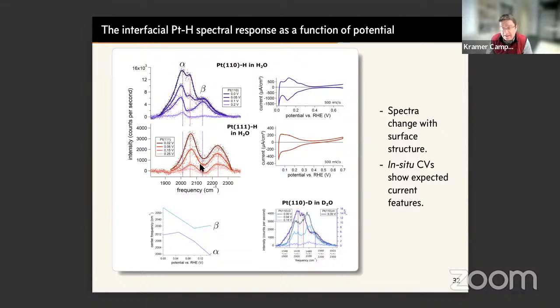Anyways, if you do the measurement now, this is the steady state measurement as a function of bias on the platinum 111 single crystal, and you pay particular attention to preparing the surface as cleanly as possible. What one sees is something that looks like this, right? So there are two spectral features that are apparent. And clearly they grow in at about the same rate as one decreases bias and moves closer and closer to hydrogen evolution. If you collect spectra in this frequency range from the double layer region out here, there is no signal, as you would expect, right? So there's no hydrogen adsorption out there, and therefore no platinum hydrogen vibrations.